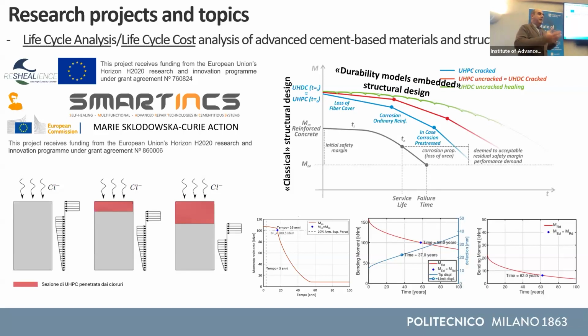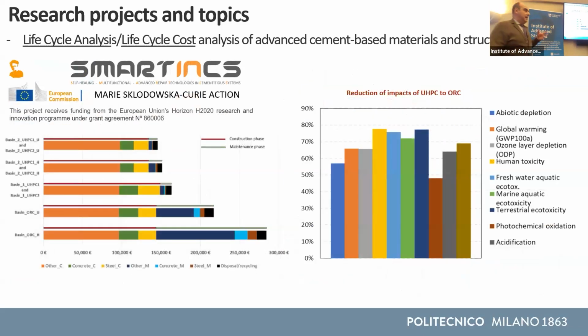In this sense, the multidisciplinarity was quite nice because we were discussing with people in timber design, and we were discussing about fire design. When you design for fire a timber structure, you calculate the time and you calculate how much thickness of timber is burned in that time, and you remove that thickness from the cross section. So we said, let's do exactly the same. If the chlorides penetrate, let's remove from the cross section, which is a little bit harsh because then we went and we tested the materials.